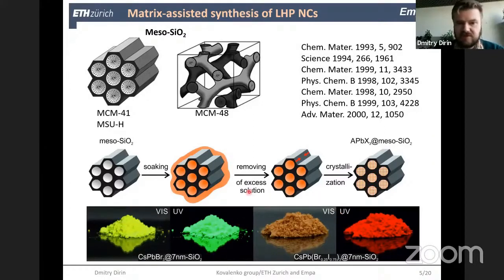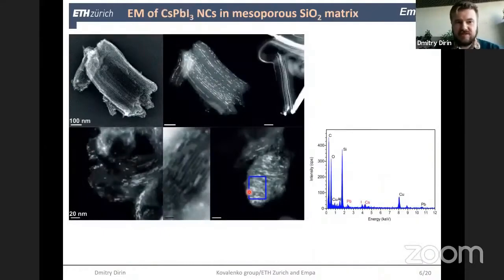This works for different colors. And so let's discuss in a bit more detail how it looks. Here we have electron microscopy images of this mesoporous silica, and then if impregnated with cesium lead bromide, or in this case cesium lead iodide, we can see nanoparticles nicely arranged in those channels. We also can see from another direction that not all channels are filled with this material, but at least the nanoparticles are nicely isolated from each other.